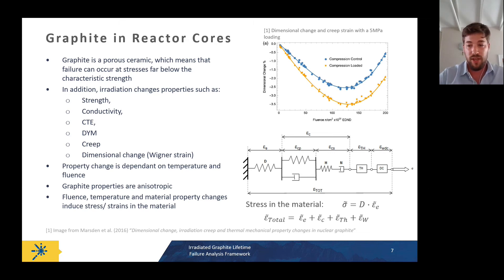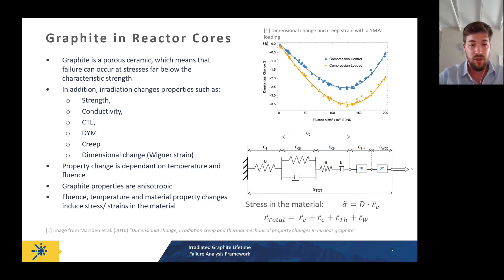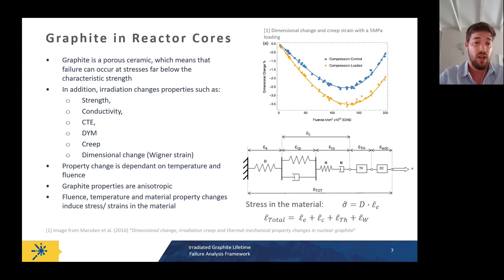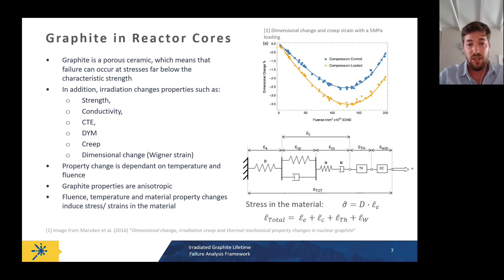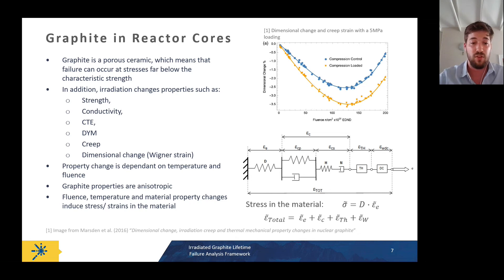When modelling stresses in graphite, all of these effects must be considered: anisotropy, dimensional change, and radiation-induced creep. The primary purpose of our model is solving the stress-strain equations incorporating all these contributions. The total strain is the sum of linear elastic strain, primary creep, secondary creep, thermal strain, and the Wigner strain — which is the radiation-induced dimensional change — and this gives us our total stress.